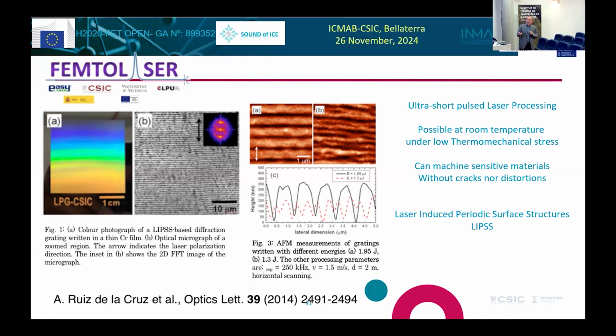And so to obtain these structures, femtosecond pulse lasers are used. And what happens, the explanation with metals of this is that the laser wave is interacting with the surface plasmon polariton wave. And so the resultant interference pattern is what you see here. That's basically it. It depends on the wavelength.